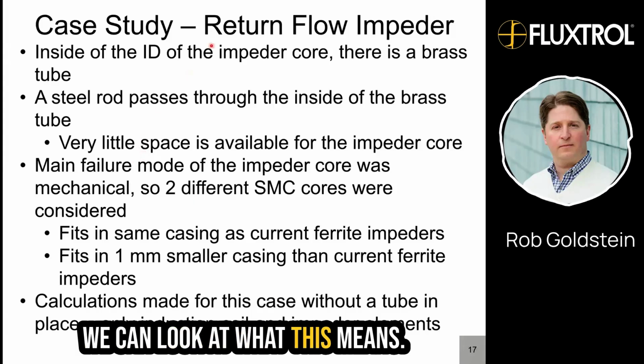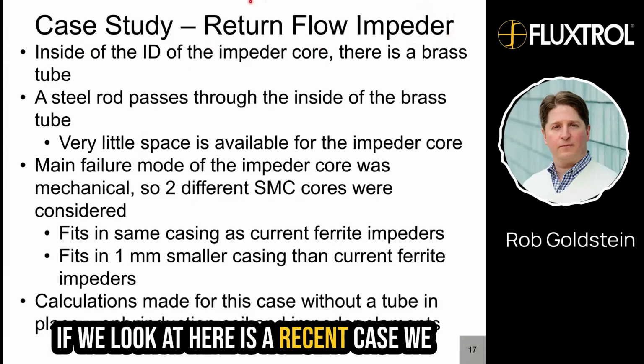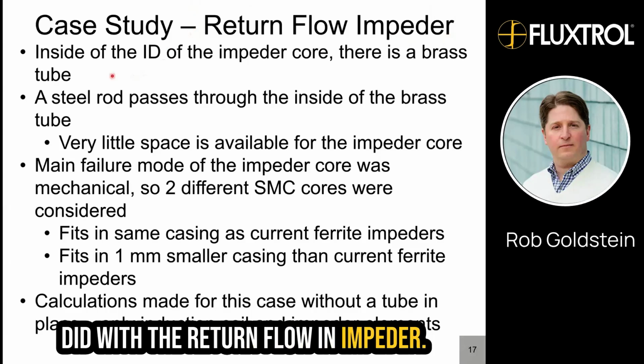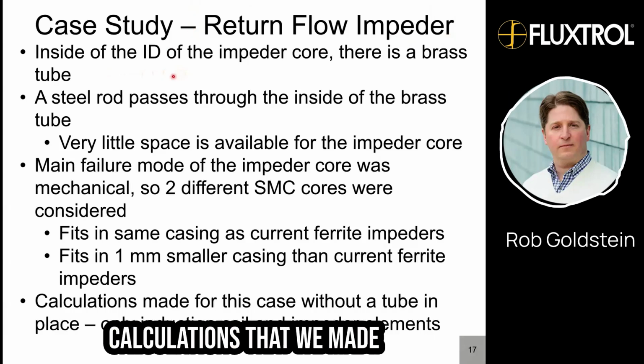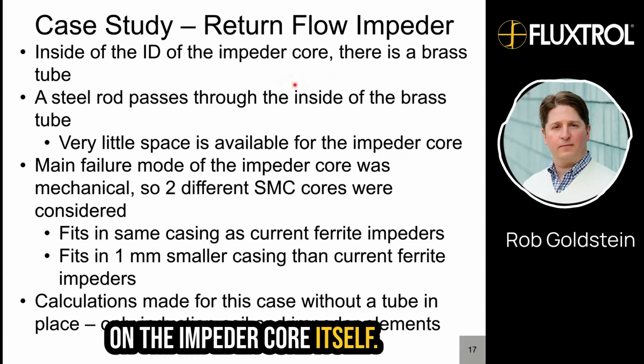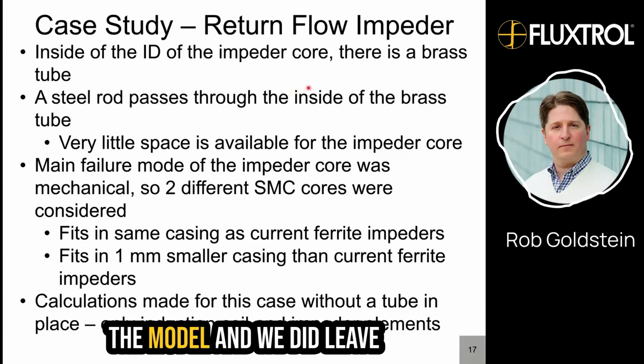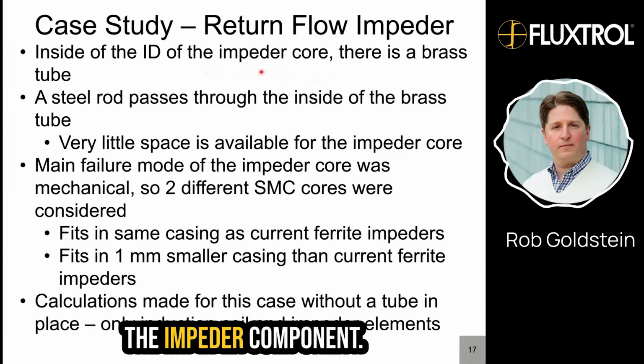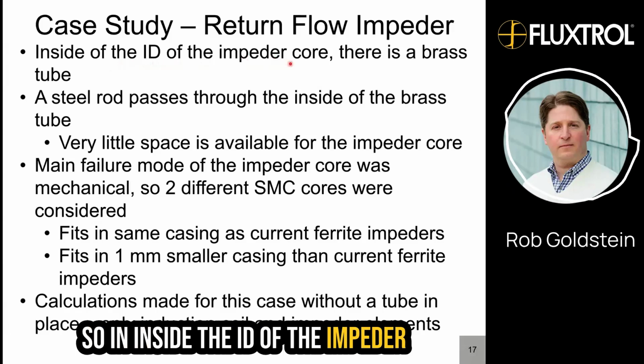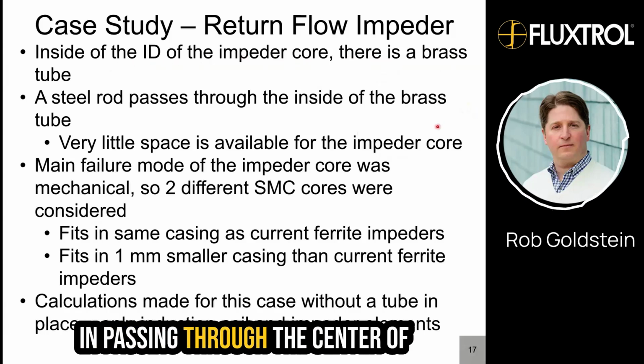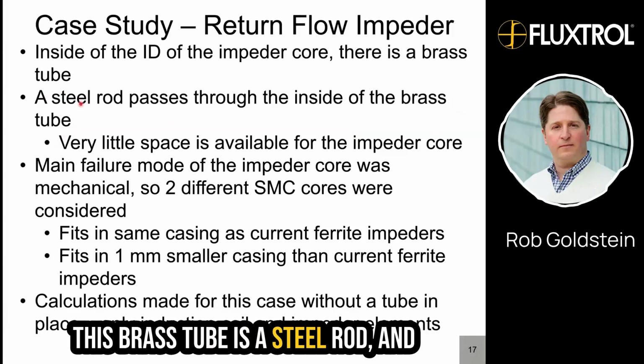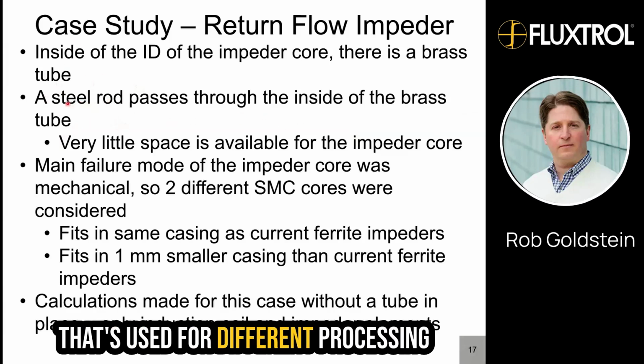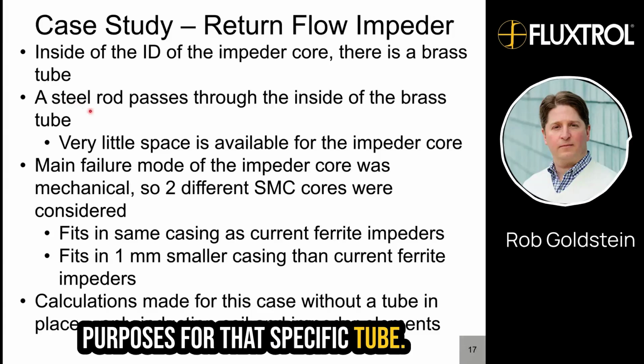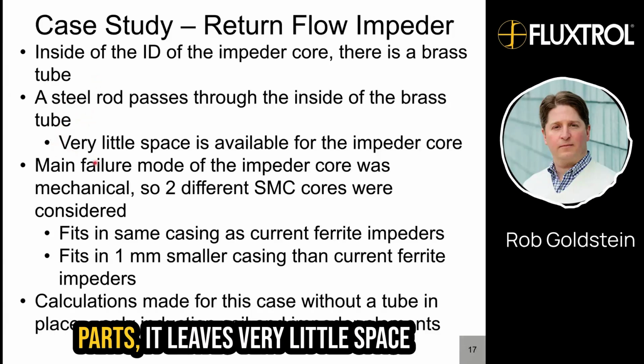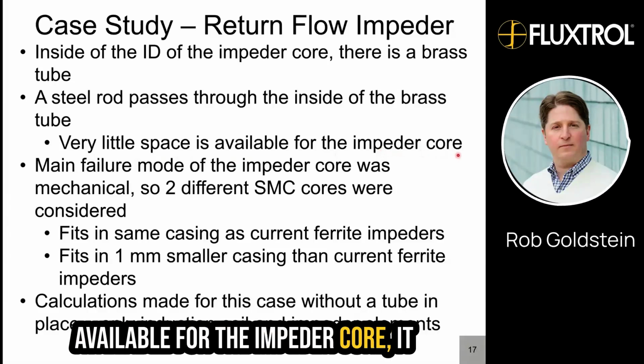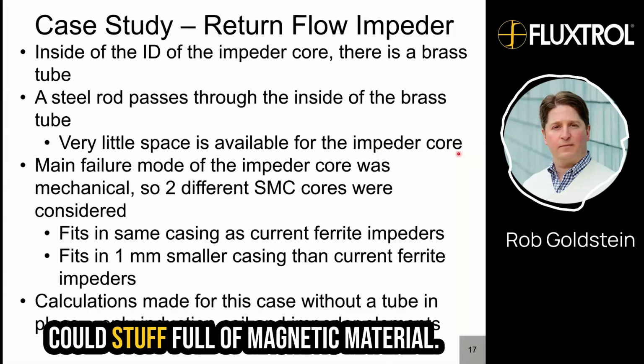We can look at what this means. Here was a recent case we did with the return flow impeder. We'll focus only on the calculations that we made on the impeder core itself, so we removed the tube from the model, and we did leave the impeder component. Inside the ID of the impeder core, there's a brass tube. Passing through the center of this brass tube is a steel rod, used for different processing purposes for that specific tube. With these other parts, it leaves very little space available for the impeder core. It really shrinks the area that you could fill with magnetic material.